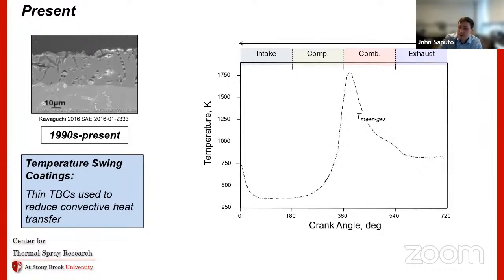So just to explain that idea, if you look at the combustion gas temperature as you move through a cycle, we have intake, compression, combustion, and exhaust. You can see it rapidly swings back and forth from about ambient temperatures to upwards of 1800 Kelvin. If you put a metal wall in this system, so it's just a normal traditional piston, you'll see that it's about a steady state temperature.